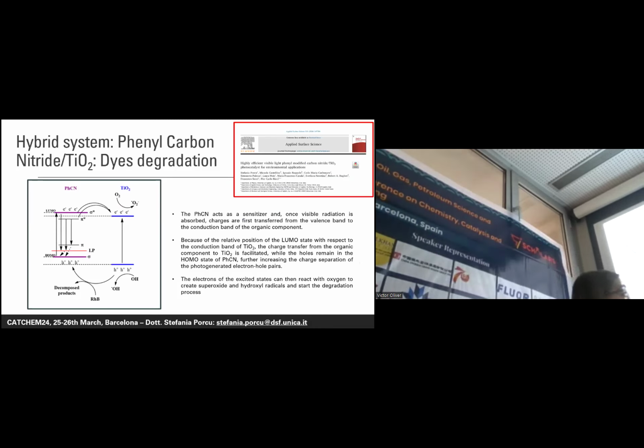So even in this case, it was just a brief resume of all the results obtained for the degradation of organic dyes. We were able to explain which degradation process is involved, meaning that in our core shell hybrid system, the organic part acts as sensitizer in the photocatalytic process, while the titanium dioxide acts as activator. So what happens is that when the light is absorbed by our organic polymer, the electrons are transferred from the valence band to the conduction band of the organic one, and then to the conduction band of titanium dioxide, and the photocatalytic process starts.